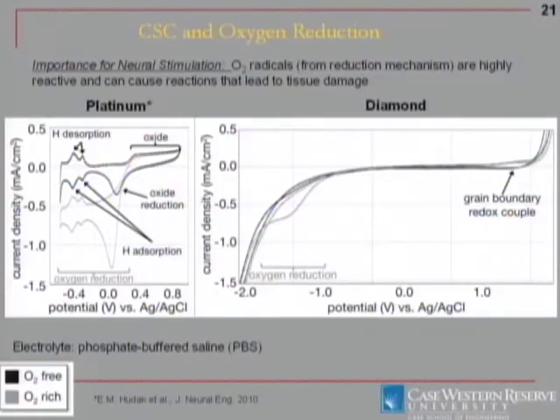So looking at the first of those in terms of oxygen reduction. Here's a comparison of the voltammograms of diamond and platinum in phosphate buffered saline. This shows the activity, and I hadn't shown you this yet. Here's the voltammogram for platinum, and here was that voltammogram for diamond, which looked actually relatively unexciting because it's just a line. But for platinum, there's a lot going on here because you get adsorption and desorption of hydrogen. You get the oxide of the metal forming and getting reduced. This is in a nitrogen environment, this dark scan.